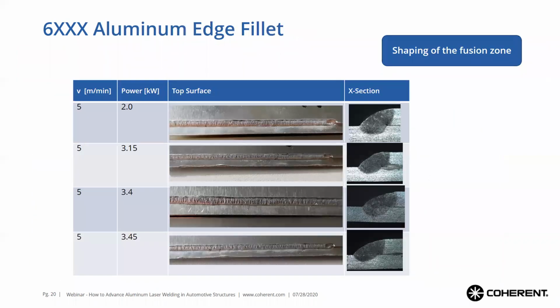Here's another example where we're looking at an edge fillet weld in 6000 series aluminum again, where we kept the speed at 5 meters a minute. That's constant. But the combined core and ring power has been adjusted from 2 to 3.5 kilowatts for these different welds that you're seeing. Also, there is no wobbling involved here, so this is a static beam just on the fillet weld. And why we changed the power, what you can see here is that we're able to control the ring and core power to essentially shape the width and the penetration of the weld, which is a very nice advantage of the arm fiber laser, to be able to shape the welds differently.